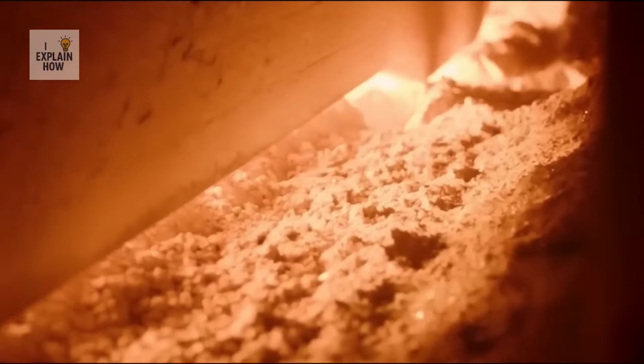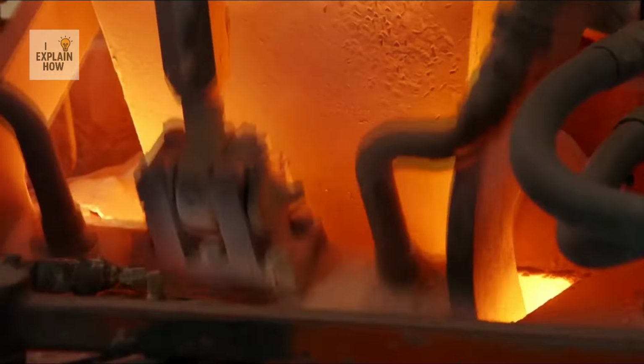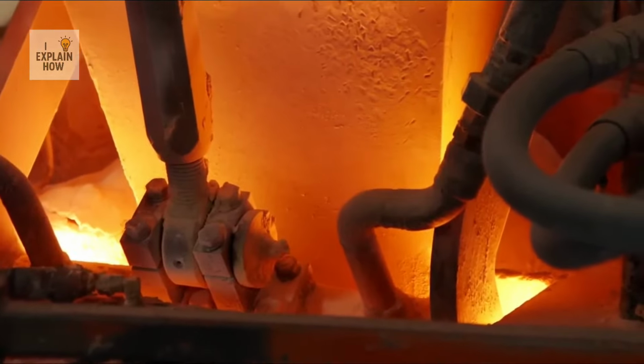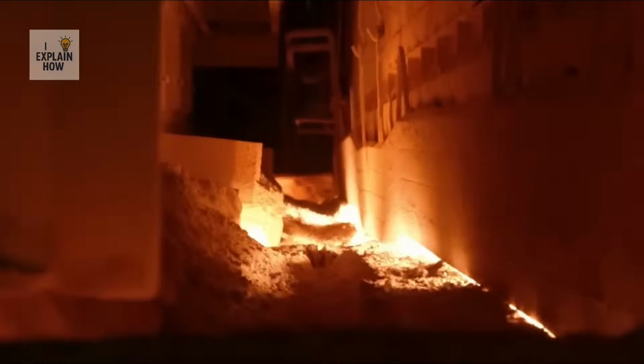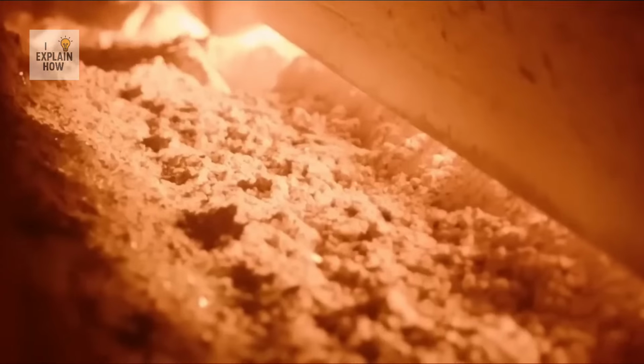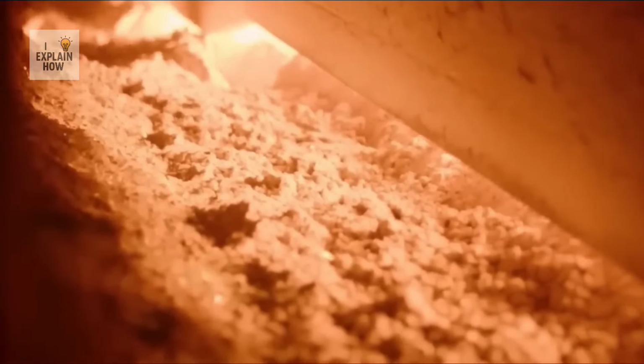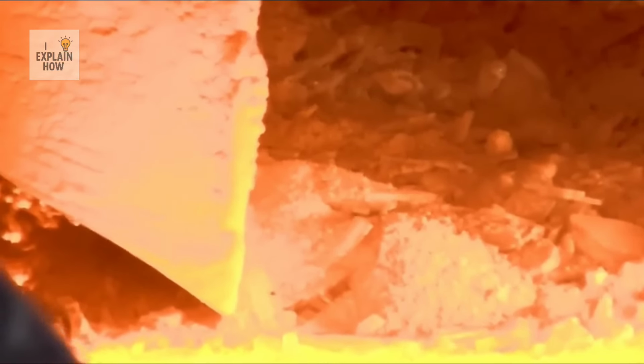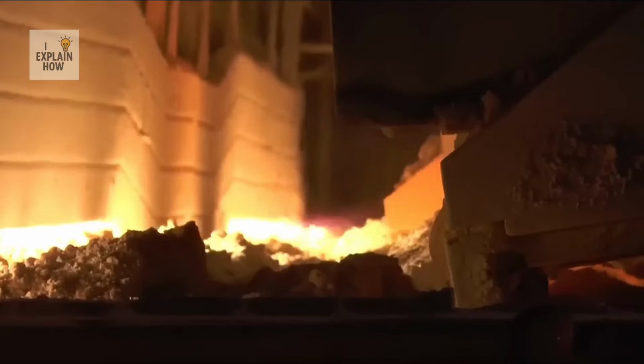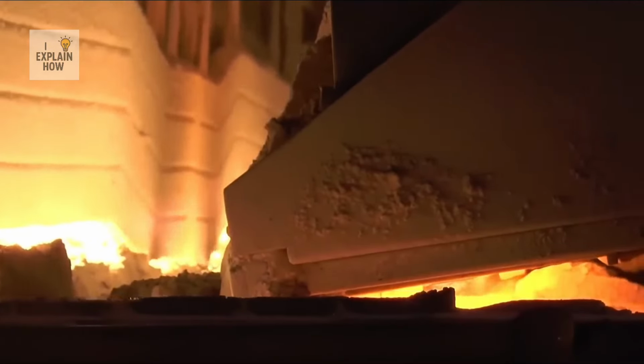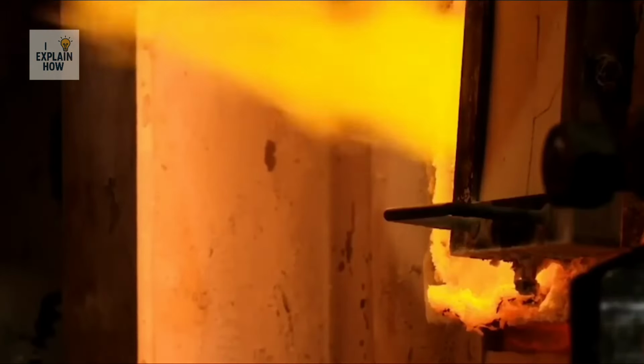This monumental furnace, built of refractory bricks, operates continuously 24 hours a day, sometimes for 10 to 15 years without being turned off. The temperature here reaches between 1500 and 1600 degrees Celsius, usually thanks to natural gas. The raw materials liquefy, releasing gases and forming a homogeneous mass. The viscosity of the molten glass is constantly monitored to ensure optimal quality.